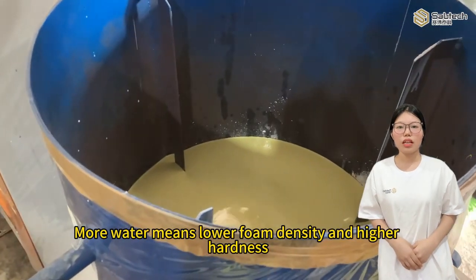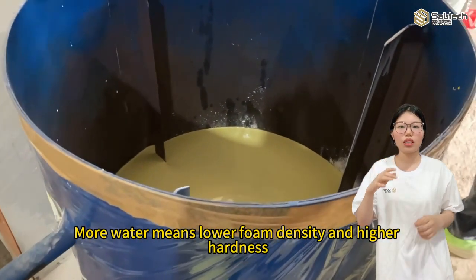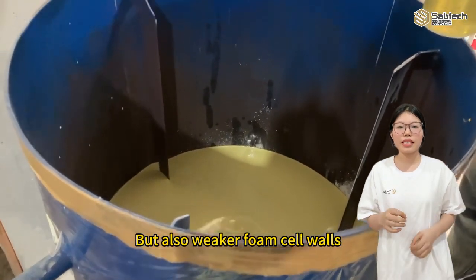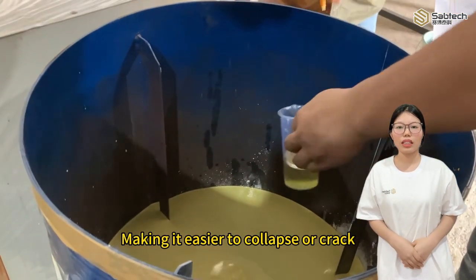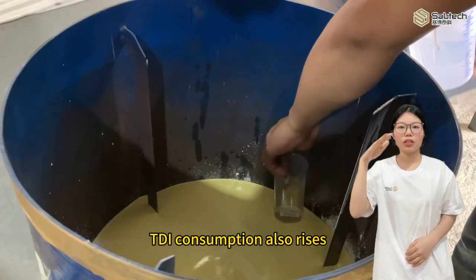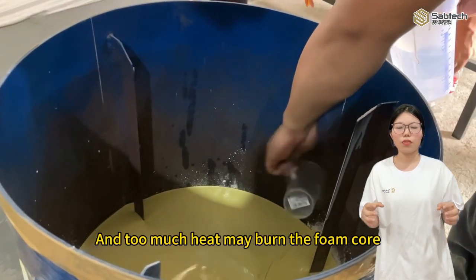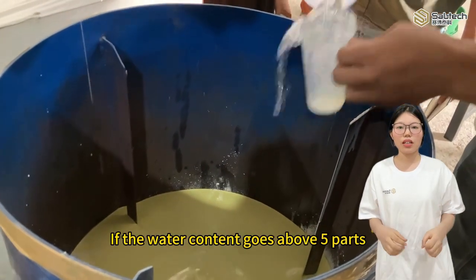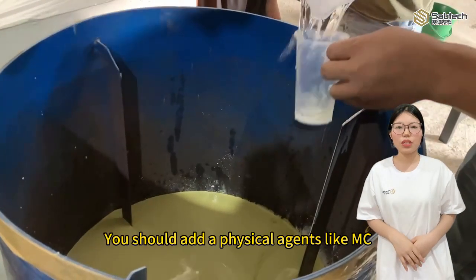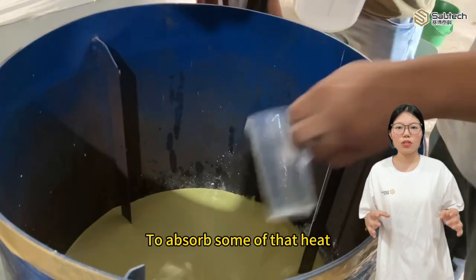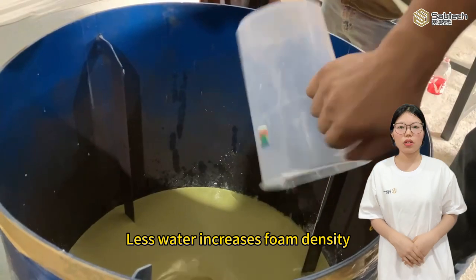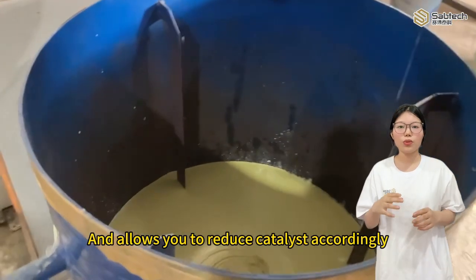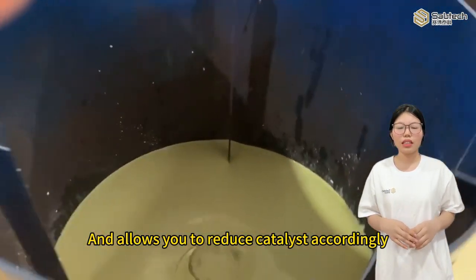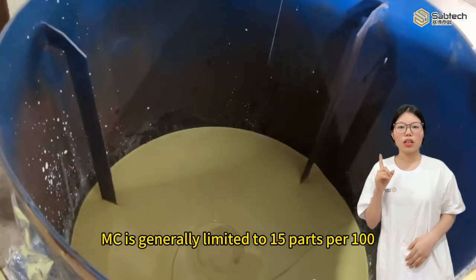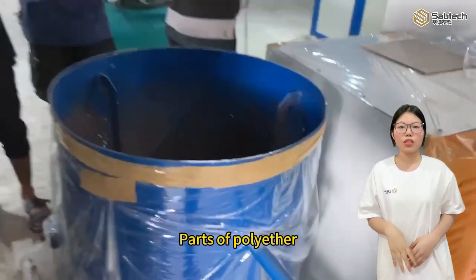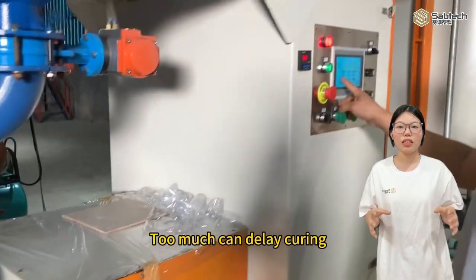More water means lower foam density and higher hardness, but also weaker foam cell walls, making it easier to collapse or crack. TDI consumption also rises, and too much heat may burn the foam core. If the water content goes above 5 parts, you should add a physical agent like MC to absorb some of that heat. Less water increases foam density and allows you to reduce catalyst accordingly. MC is generally limited to 15 parts per 100 parts of polyether. Too much can delay curing.